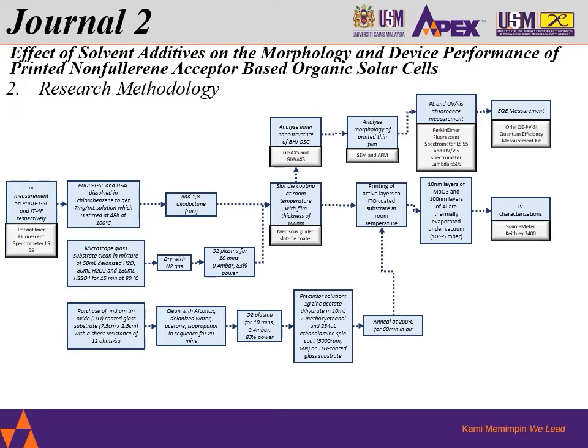Moving into the research methodology of this journal. First of all, photoluminescence measurement was done on the pure acceptor and pure donor respectively using this machine. And then it is dissolved in chlorobenzene to obtain a 7 milligram per milliliter solution, which is stirred for 48 hours at 100 degrees Celsius. And then there's an addition of 1,8-DIO, with different concentrations as the study suggests.